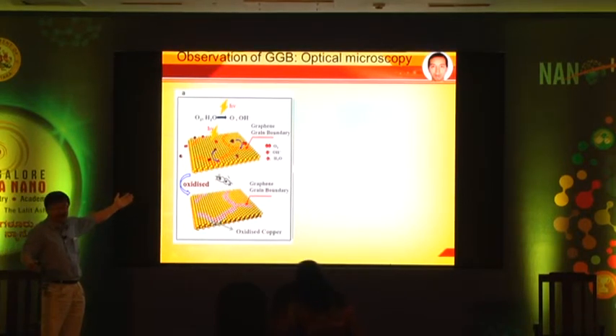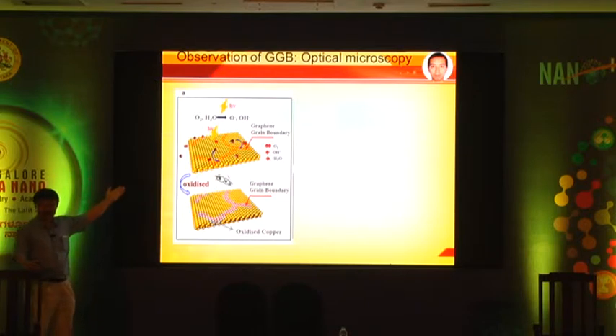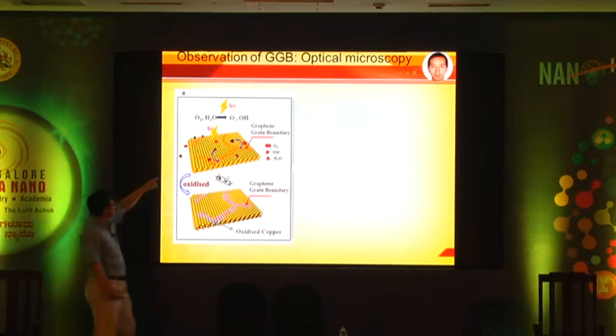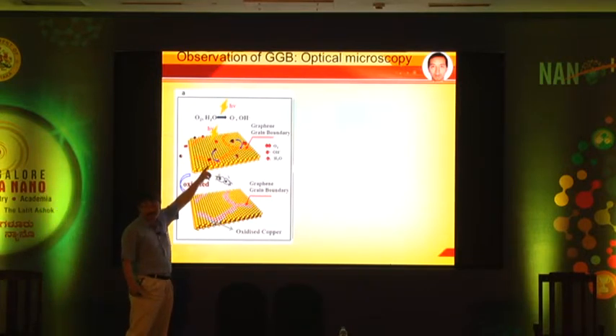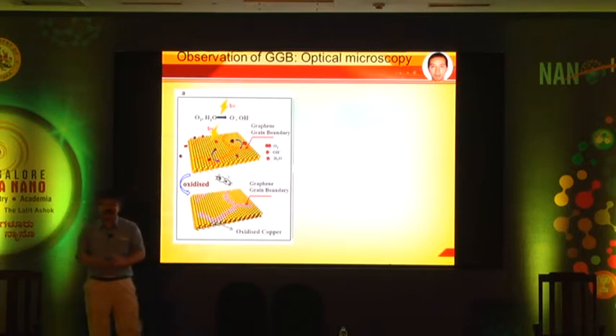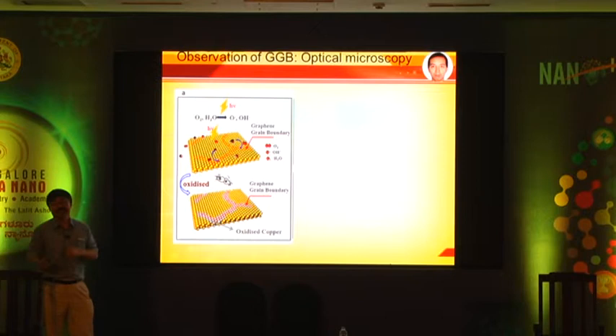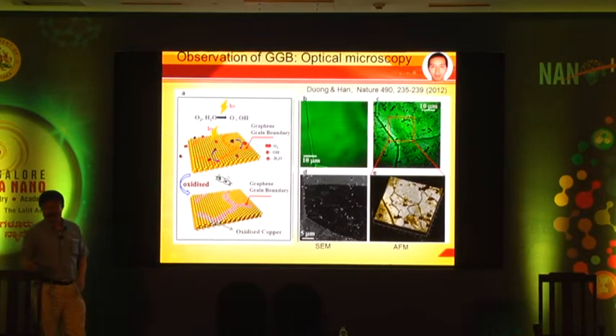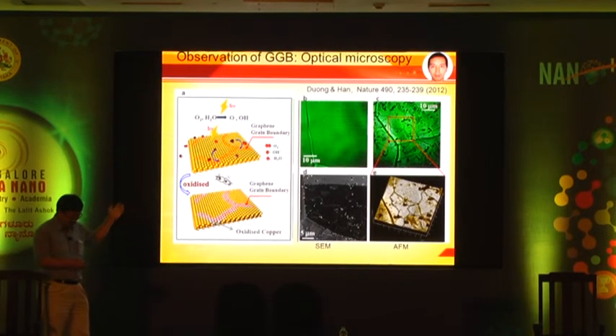Here we have this copper substrate. We have graphene on it. And then you irradiate this substrate with oxygen radicals. Interestingly, these oxygen radicals penetrate through the graphene on top and then oxidize the underlying copper. So the copper has a sort of volume expansion due to oxidation. This is what we can observe through an optical microscope. So the idea is very simple, but the consequence is that we can observe grain boundaries using just a simple optical microscope. We did this several years ago, and we confirmed this is really what happens.